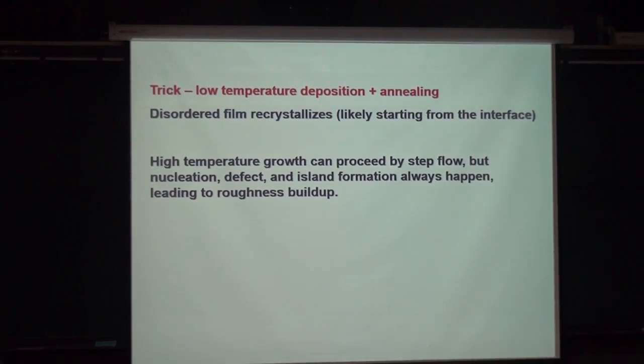So we tried that for many years, and then we thought of the other way: let's do a low temperature deposition. And so when you deposit atoms on the surface, the atoms are simply frozen on the surface. They're in an amorphous structure. It's not ordered, but then you raise the temperature, you anneal the system, and then the system recrystallizes starting from the substrate. And so you form the single crystal. And if you have just the right amount, it becomes a perfect film. It's a very simple trick.